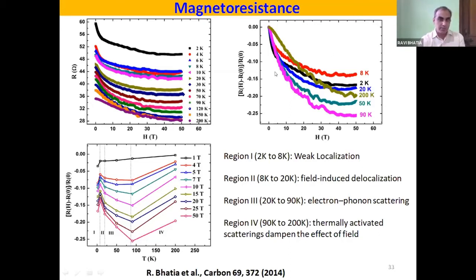So we had to convert these graphs into this particular figure on my left down corner. So there is some feature which can be understood here. At 1 Tesla, 4 Tesla, 5 Tesla, and up to 50 Tesla, we took out all the points and presented them in this manner, where the temperature is on the x-axis. Now the situation gets a little clearer with the plot here, that at the lowest magnetic field, there is hardly any change in the magnetoresistance. As you go to 4 Tesla and 50 Tesla, there is the same trend at all temperatures.